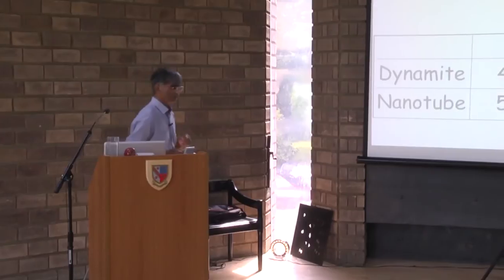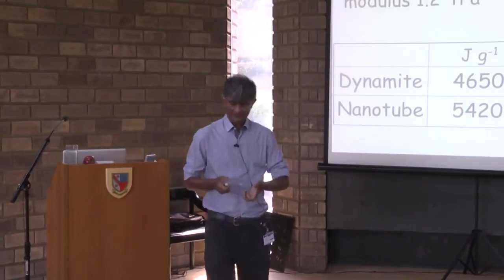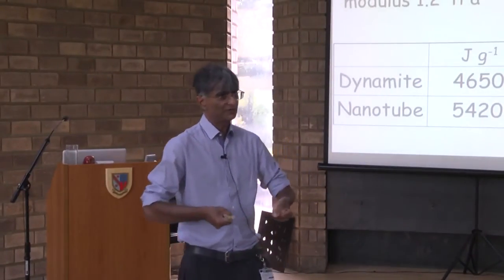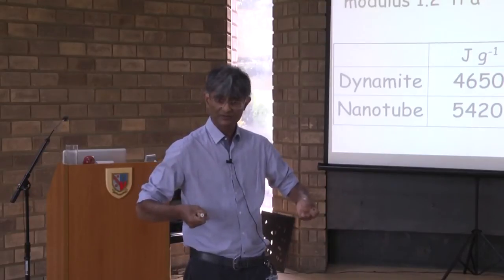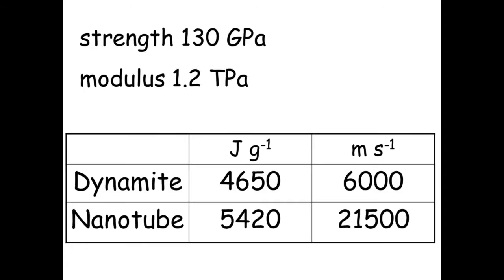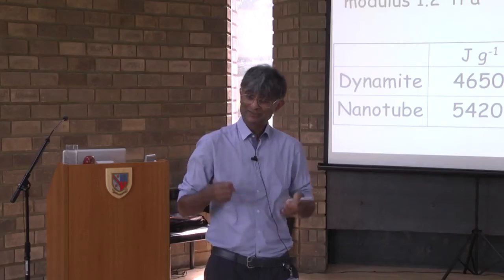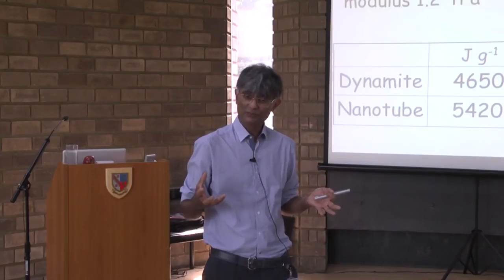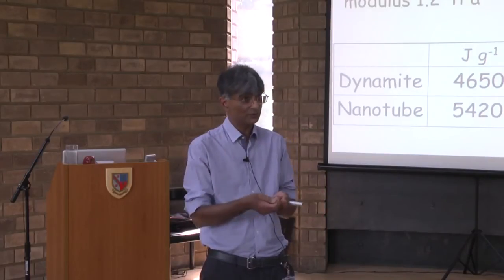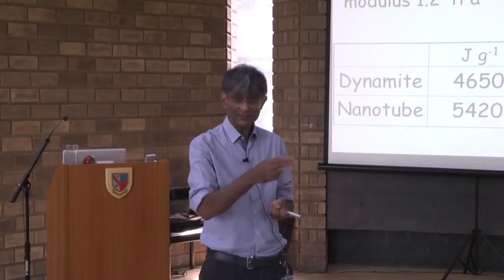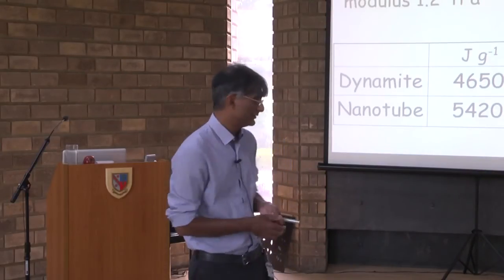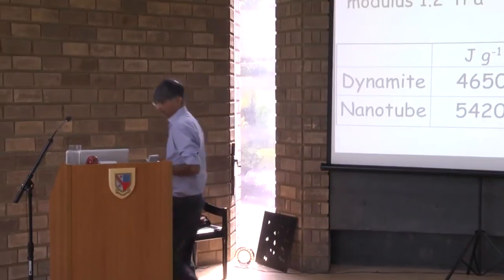Okay. The other problem with very strong materials is that, of course, if you load the carbon nanotube to 130 gigapascals, then the amount of energy stored in it is more than dynamite. And because its stiffness is bigger than dynamite, the velocity of the explosion, and Chris might talk about that, is much, much greater. Yeah, so this would not be a safe engineering structure. It's like when you get whiplash when a chain which is pulling a heavy load breaks. So nanotubes are not the answer.